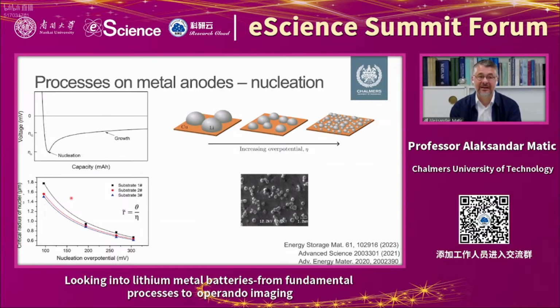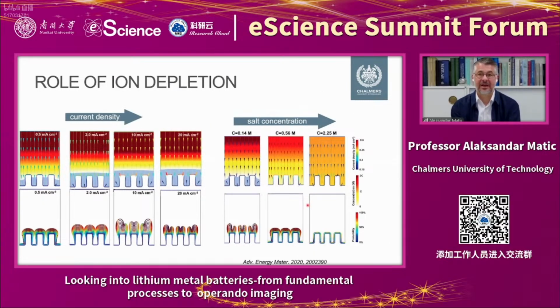And actually the size of the initial objects is quite big. I think the simulations overestimate the size a little bit, but still you are of the order of somewhere between a few hundred nanometers to almost a micron. And you can see here in this SEM image of deposited lithium onto a copper surface that the small crystallites formed in the beginning are of the order of half a micron or similar.